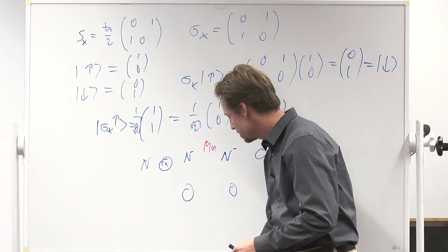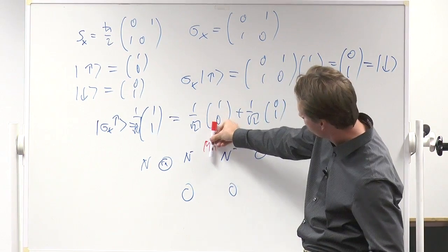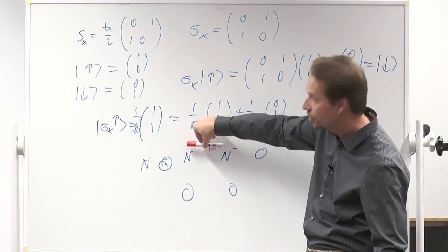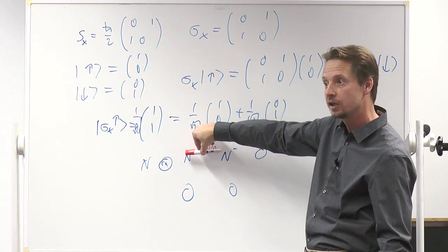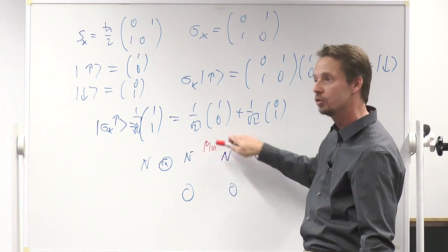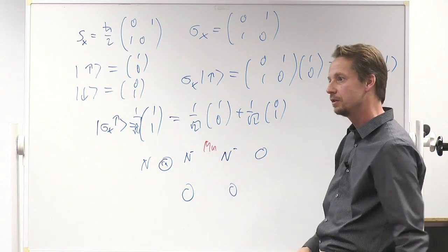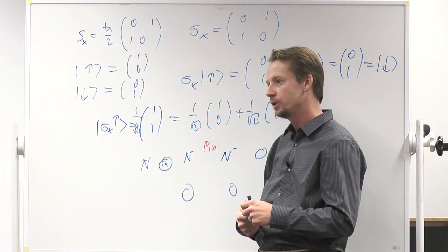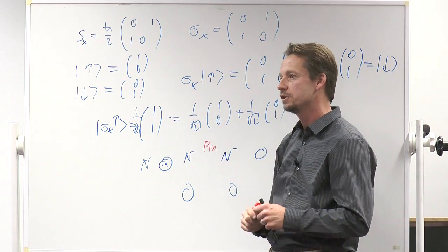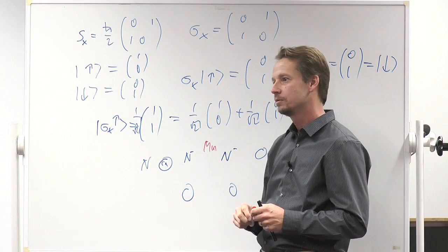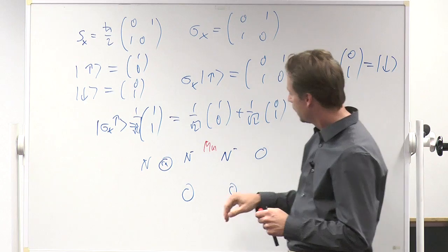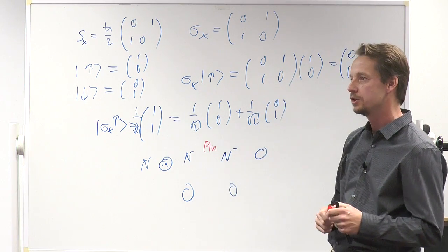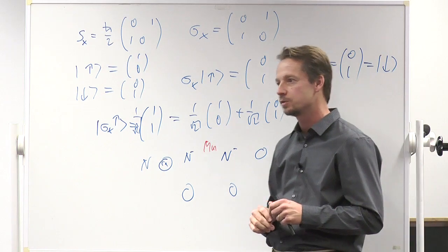So if this manganese spin is pointing in the perpendicular direction, it has a certain energy. If it's pointing in an in-plane direction, it might have a different energy. And that's set up by the local symmetry of your binding site here. And that difference in energy, we call that magnetic anisotropy. That is something that gives rise to these finite energy offsets, right? And I want to take quite a bit of time, actually, to explain how this comes about using something like these spin operators, in a few slides, basically.